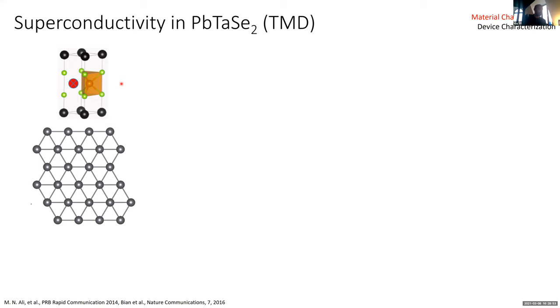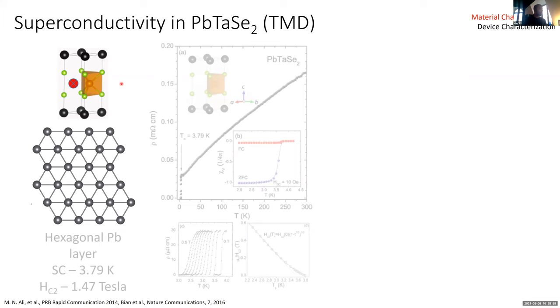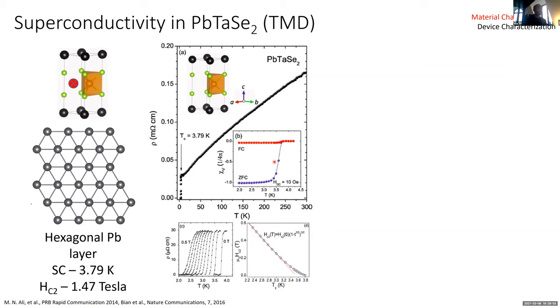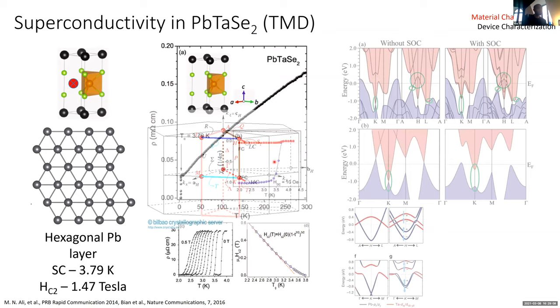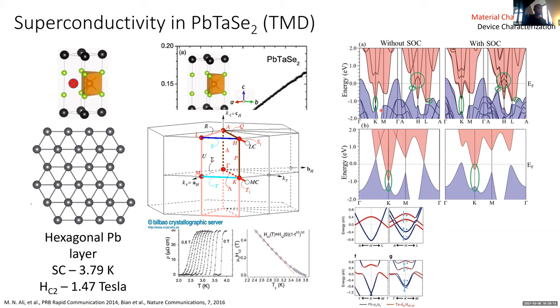So what happens? Well, it was interesting that it superconducts and people are still investigating the nature of the superconductivity, and that's all fun. And in terms of the electronic structure, it behaved kind of as expected. The Dirac cone appeared at K like it's supposed to, along with some other tangential or so-called accidental crossings. And when you apply spin orbit coupling, because this thing has a lot of it, sure enough, because it's lacking certain types of symmetries, those gap, but you ended up with some other extra crossings. And so this compound ended up being the so-called first Weyl nodal line semimetal.